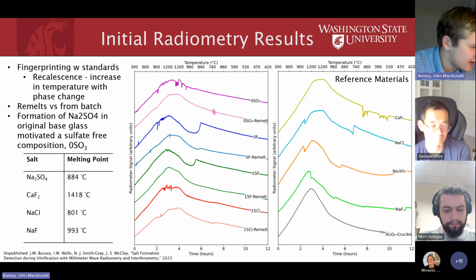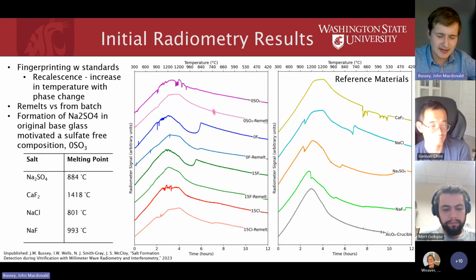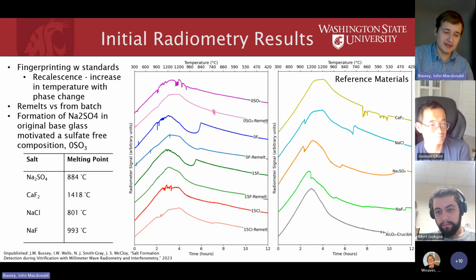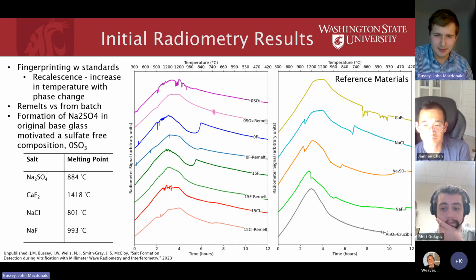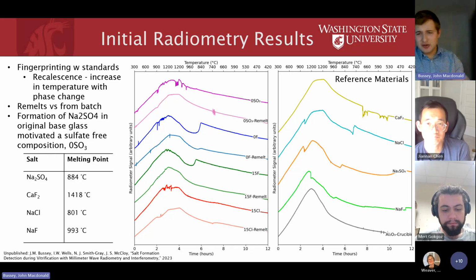So our baseline didn't work particularly well, but that's perhaps an interesting feature about sulfate. Again, mentioning that the models are perhaps too liberal in estimating sulfate presence, and this is another example of that. So we measured those, then we measured several reference materials of the salts that we thought might form, and then tried to match them up.